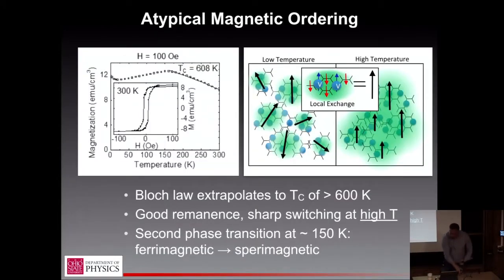Let's look here and think about the mechanism of the magnetism. So at low temperature, and here I've sort of cartoonishly indicated regions of high structural order, or grains of high structural order, with intermediate blocking regions that are disordered. So at low temperature, you have some local magnetic ordering. Think of it maybe as superparamagnetic ordering. But grain to grain, that ordering is not well defined. And this low temperature phase means below about 150 Kelvin. You can see the magnetization's dropping. So this behavior, and if we apply a magnetic field, we can recover this. It's sort of like a spin glass, but it's not really a spin glass.